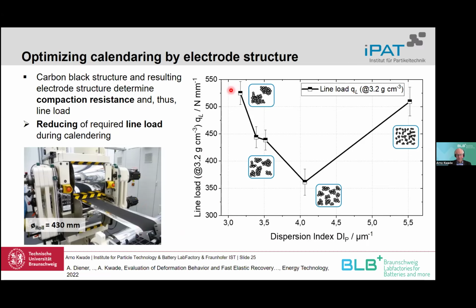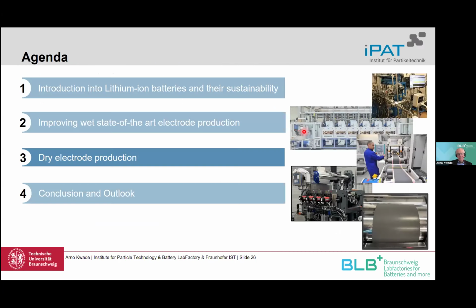It is especially due to the elastic recovery, which is much higher. Then we go down to a smaller line load at a dispersion index of about 4. And if we increase the dispersion index and have almost only aggregates, then we need again a higher line load, against the elastic recovery, to come to the final density, in this case 3.2 gram per cubic centimeter. Okay, this was some insight into the production of wet produced electrodes. And now I would like to come to the second topic of my talk.